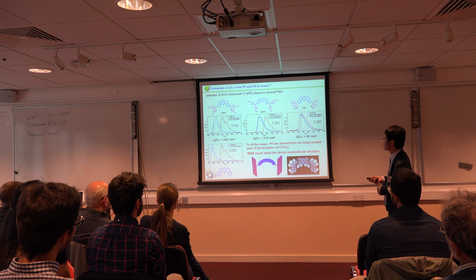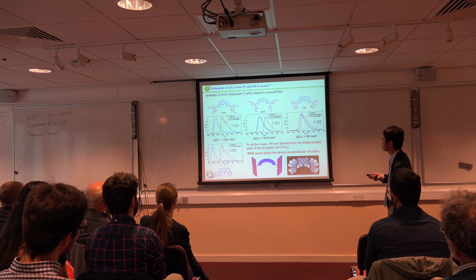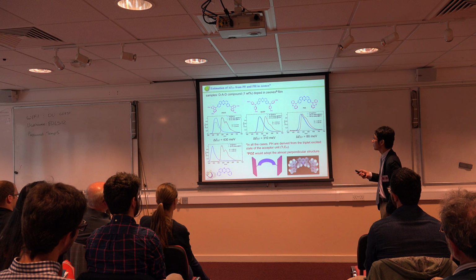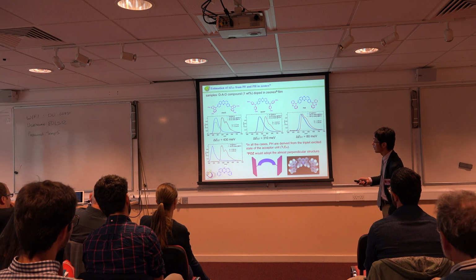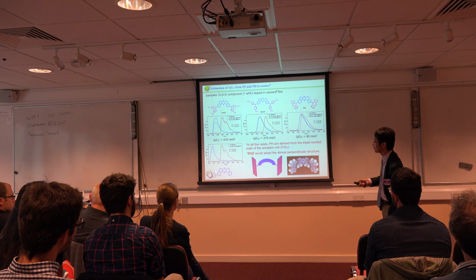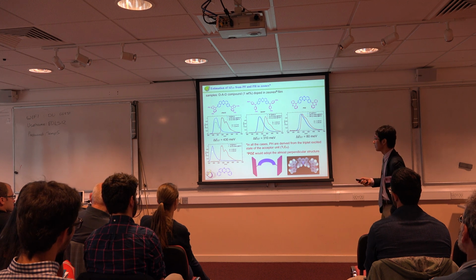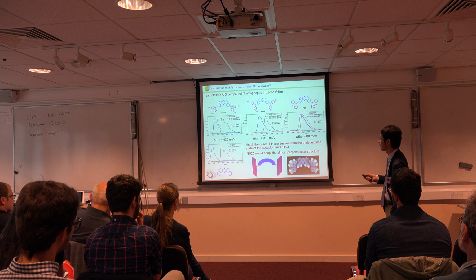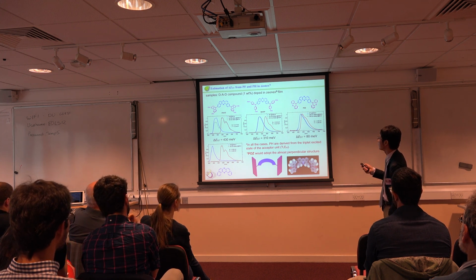Okay, so from the physical properties at room temperature and low temperature, we found that the triplet state comes from this acceptor unit shown here. As you can see, the spectra at 80 Kelvin are very similar to this compound, meaning that in these cases the locally excited triplet state comes from the acceptor unit.